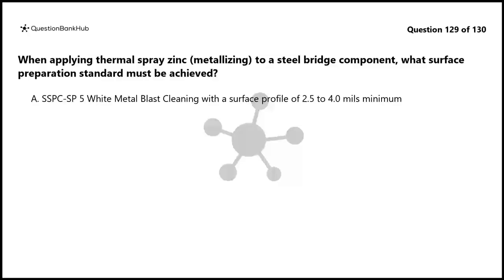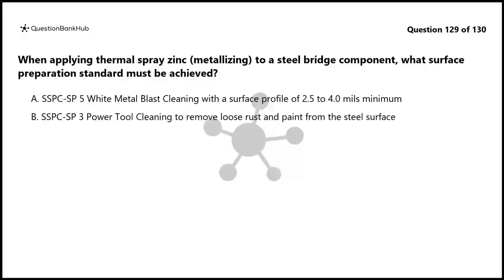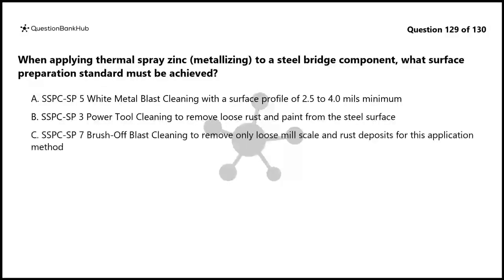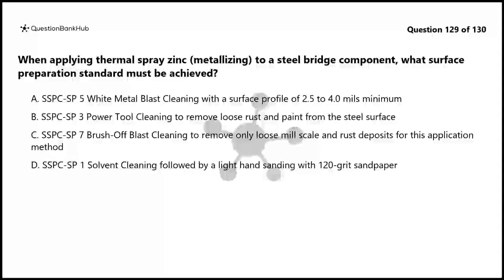Question 129. When applying thermal spray zinc, metallizing, to a steel bridge component, what surface preparation standard must be achieved? A. SSPC-SP 5 white metal blast cleaning with a surface profile of 2.5 to 4.0 mils minimum. B. SSPC-SP 3 power tool cleaning to remove loose rust and paint from the steel surface. C. SSPC-SP 7 brush-off blast cleaning to remove only loose mill scale and rust deposits for this application method. D. SSPC-SP 1 solvent cleaning followed by a light hand sanding with 120 grit sandpaper.